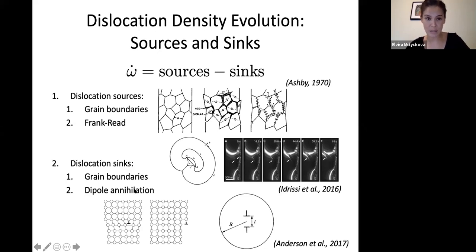This process requires climb of dislocations. What it means is that in a crystal, you can have two dislocations of opposite sign. If you think of them as edge dislocations, a dislocation in general is just a plane of atoms, or of vacancies, shoved into a grain or crystal. Dislocations of opposite sign would be one plane shoved in from the opposite side than the other. So the dislocations of opposite sign would attract each other and eventually merge. But in order to do that, they need to exchange atoms or vacancies, and this would require climb. So this is a climb-limited process.